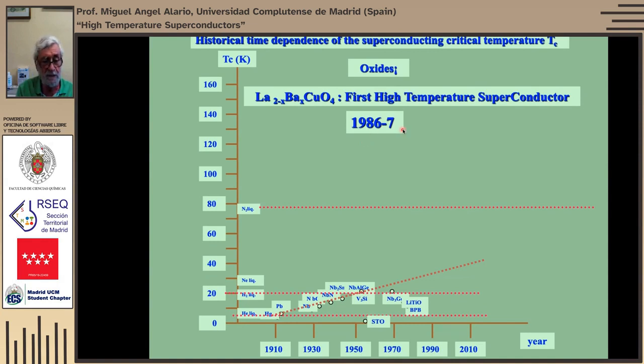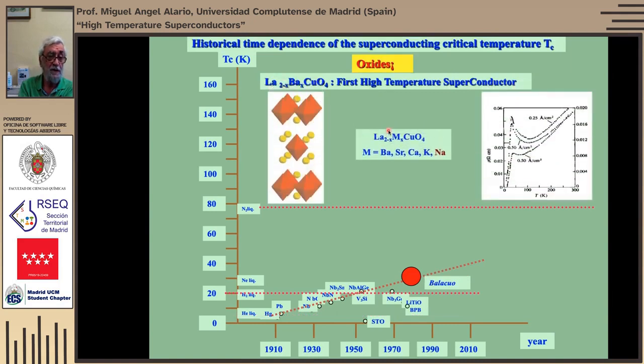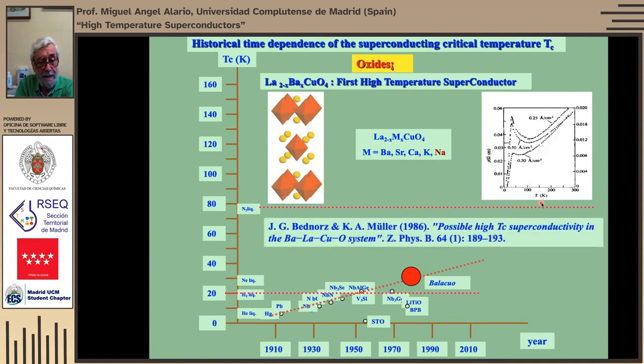In this particular case of superconductivity, it was the discovery of this material, which is an oxide and has a structure related to perovskite. You can see here that the critical temperatures are much higher. After this, a lot of people started to work on superconductivity because these materials were relatively simpler than all the ones we've seen before. And that's the article that took them to the Nobel Prize, as we mentioned before.